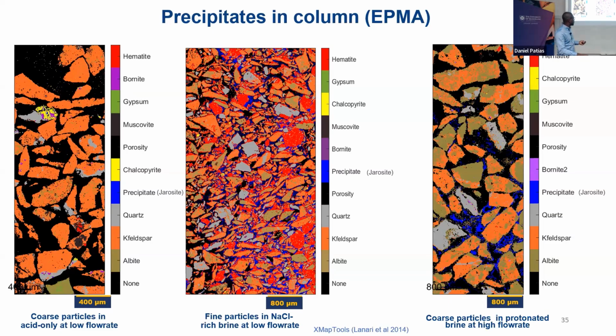So this is what we did. We observed for the protonated brine, jarosite formation mainly at the entry points, and at the exit, not much. But for the fine material in sodium chloride-rich brine, you have it preferentially forming along the flow pathways and all the way throughout the column. You also can see some ferric oxide balls which are forming. For the acid, we don't see much - what we see is just tiny bits of jarosite forming where your copper sulfides are.